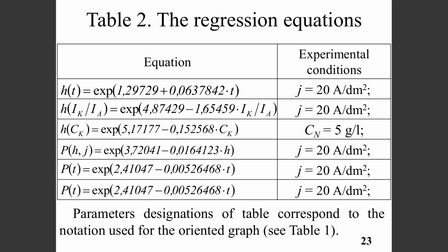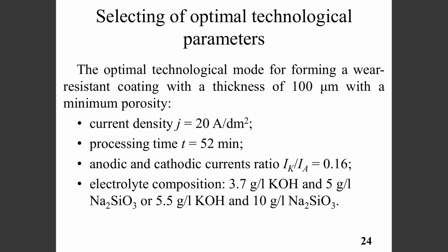Regression models of the relationship of various parameters effects with parameters reactions were also obtained on the basis of available experimental data using the StatGraphics program. Some regression equations are shown on the slide. Based on the model 18 and the obtained regression equations, a methodology for selecting technological parameters for producing microarc oxidation coatings was developed, with the help of which the optimal technological mode for forming a wear-resistant coating with a thickness of 100 micrometers with minimum porosity was found. The parameters of the obtained technological mode are presented on the slide.